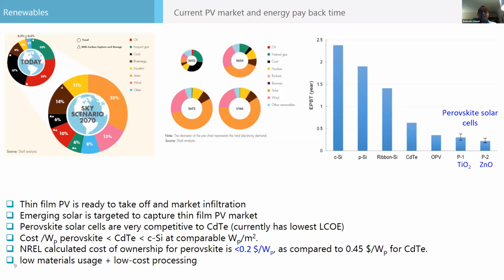And the lowest we can see is from perovskite solar cells, because the thickness is less and we don't need high temperature annealing. For example, with titanium dioxide, to convert the anatase state to rutile, you anneal at 500 degrees centigrade. This is a little bit high, but if you replace titanium dioxide with SnO2, another very good n-type conductor, or zinc oxide, or an organic one, the energy payback time will be even less, because we just need to anneal at 100 degrees centigrade.